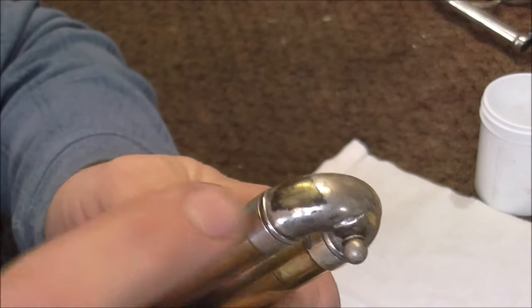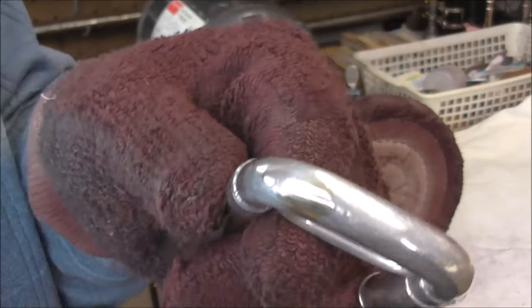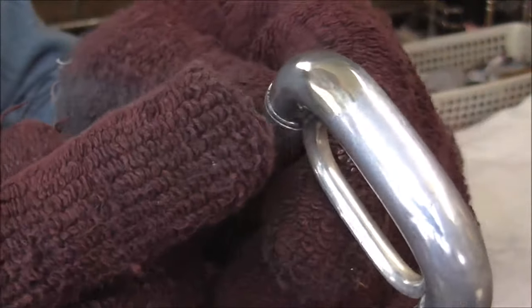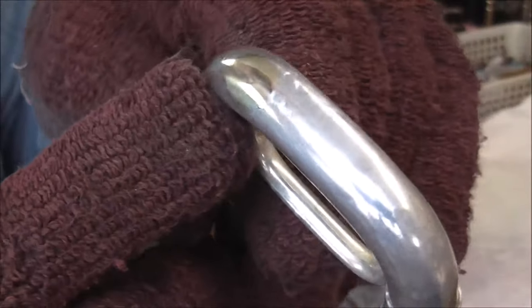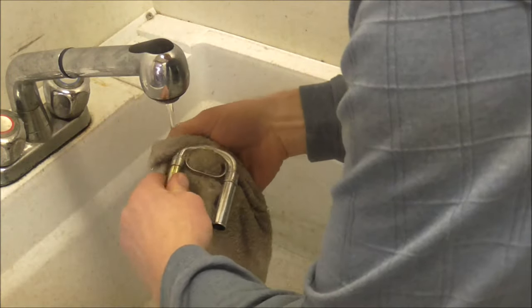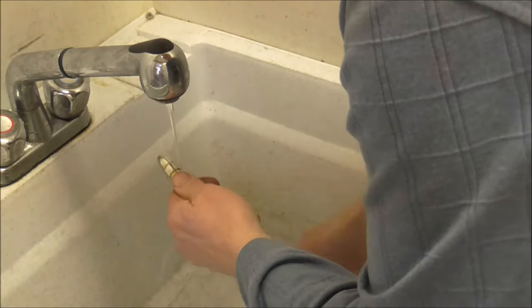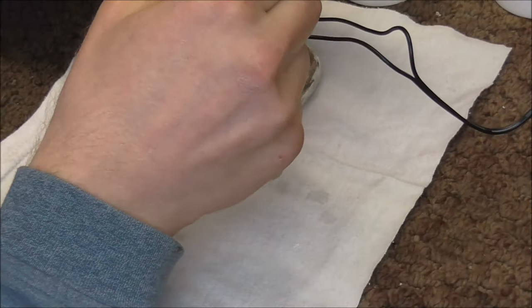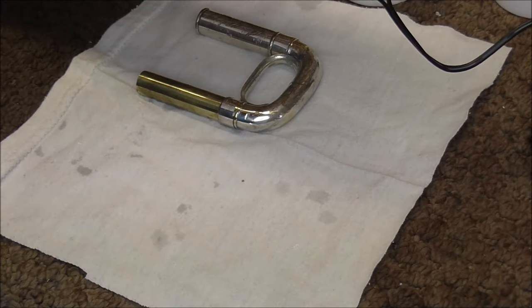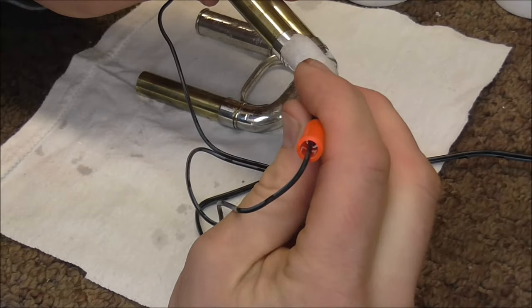This is the third valve slide, and there is another spot that needs to be plated. If you watched the last video on me restoring this cornet, you saw me patch the cracks in the slide right there. The yellowish spots are where I put the silver solder and patched the cracks. I also need to be careful when I wash this not to touch it, because the oils on your hands can cause problems with the plating. I am going to hook this up and plug in the unit, unplugging it every time so things do not arc and get ruined.